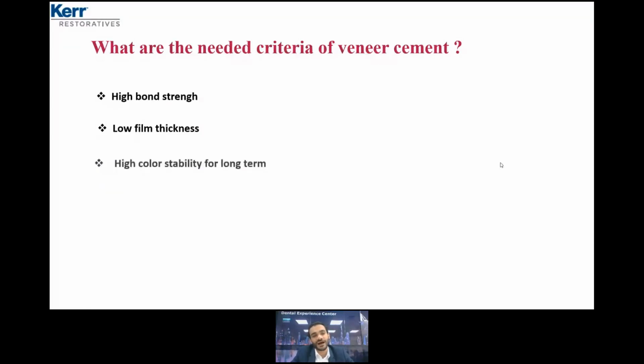But also we need to have the veneer cement with a high color stability. We mentioned high color stability in the dual cure cement and the self-adhesive resin cement. But here, it's the most important to have high color stability because the veneer is only like 0.3, 0.4 millimeter, which means it's almost translucent. And the color of the cement will be clear through the veneer. So we need to have a high color stability of the cement for a long time, for the long term.